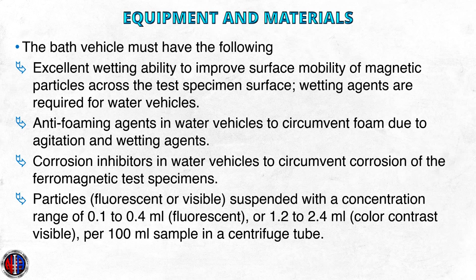Anti-foaming agents in water vehicles to circumvent foam due to agitation and wetting agents, corrosion inhibitors in water vehicles to circumvent corrosion of the ferromagnetic test specimens, particles, either fluorescent or visible, suspended with a concentration range of 0.1 to 0.4 milliliters of fluorescent particles, or 1.2 to 2.4 milliliters for color contrast visible particles per 100 milliliter sample in a centrifuge tube.